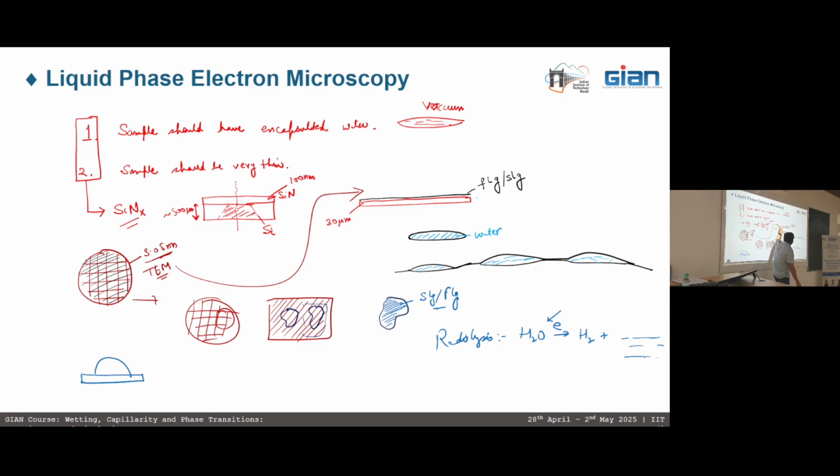So you should explore methods to make it ultra flat. Maybe one is to put it between 2 glass slides and apply a medium pressure so that it becomes flat. The next important step is that when you put this holey carbon grid on top of that, the holey carbon side should be facing downward, so there are enough van der Waals interactions between your holey carbon and this single layer graphene so that it sticks to it.